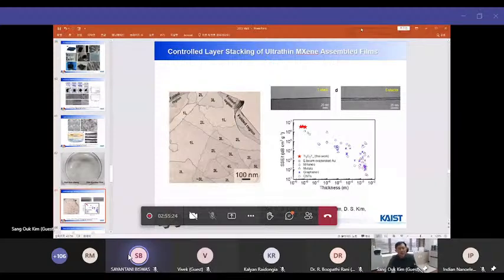And we also applied this approach for MXene assembly. MXene is hard to obtain as a large area film, because if you use typical vapor deposition, it tends to form a bulk phase rather than a thin MXene layer. So the only way is to use exfoliated platelets assembled in the 2D structure. So that's why we used the Marangoni effect. And by incorporating our method, we could obtain a well-defined, large area, minimally stacked MXene film, and identify the EMI shielding impact of this material.